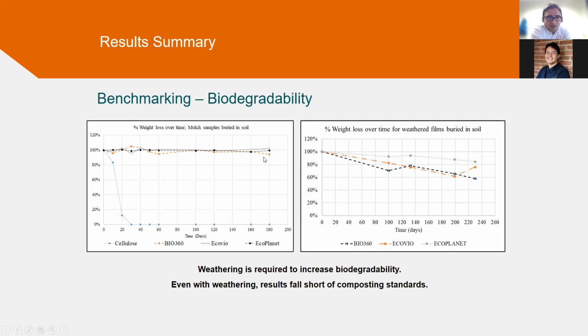So this is a problem, and this kind of correlates with some of the problems that, hey, these films might not actually really biodegrade in the time frame that we need to. One of the things that we found out quickly is that the pristine films don't have any weathering, or they haven't been exposed to light, wind, rain as a traditional film will. So we developed a protocol to do a weather sample and then biodegrade it.